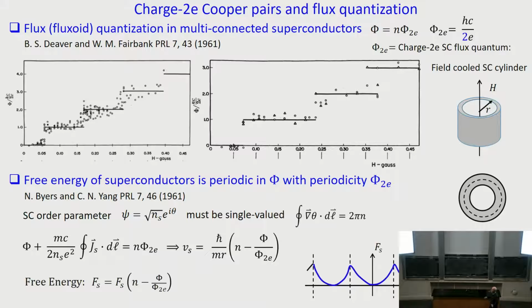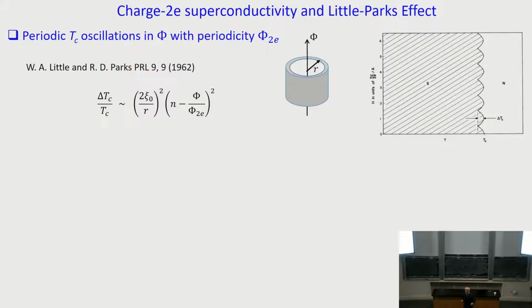Free energy quantized this way, 1961, 1962, Little and Parks, they're genius. They thought, free energy oscillates, everything must oscillate. So they say Tc must oscillate. And this is Tc as a function of flux, magnetic flux. It really, truly oscillates. But it's very difficult to detect that.